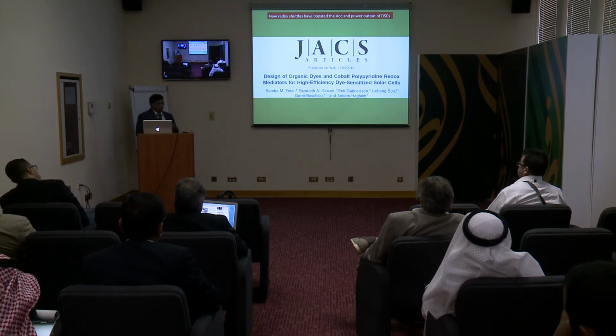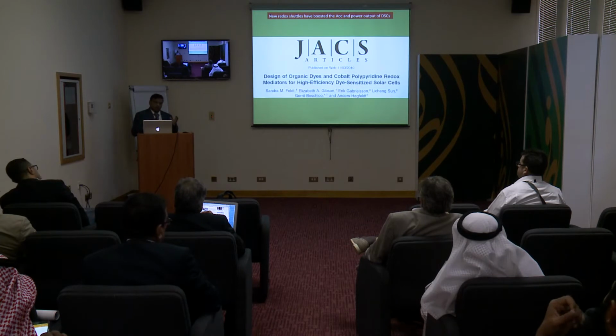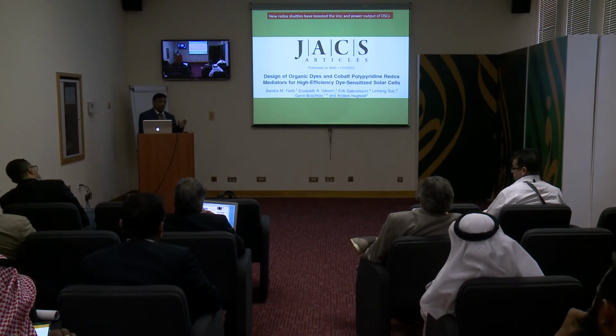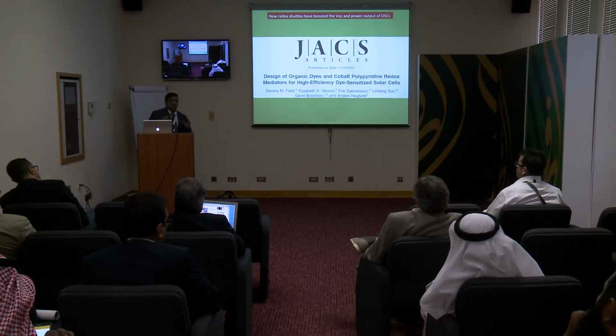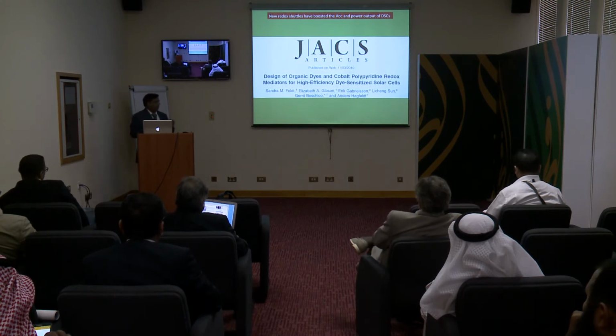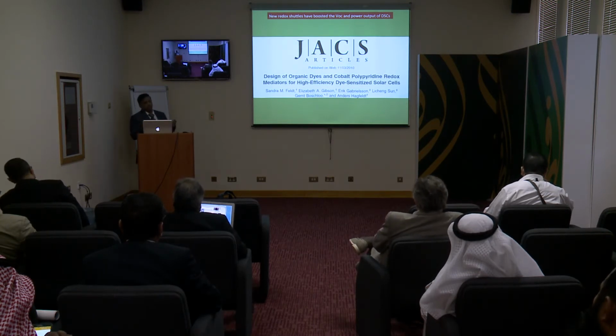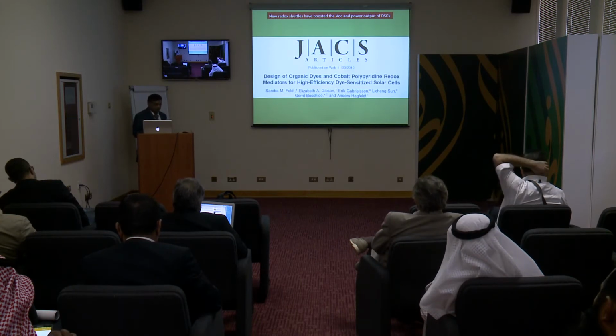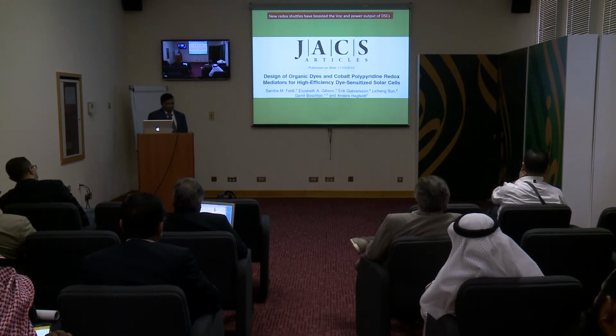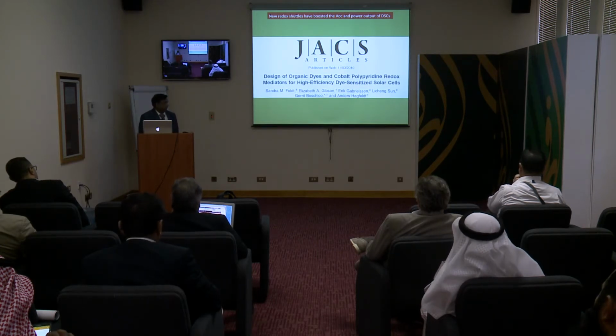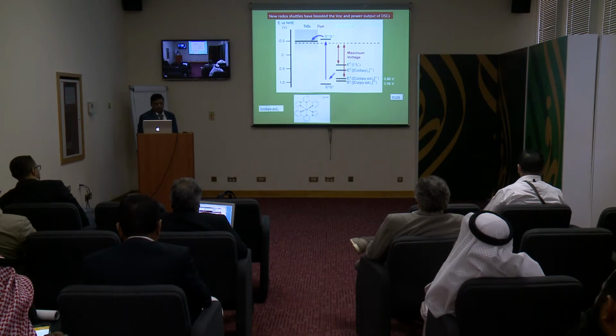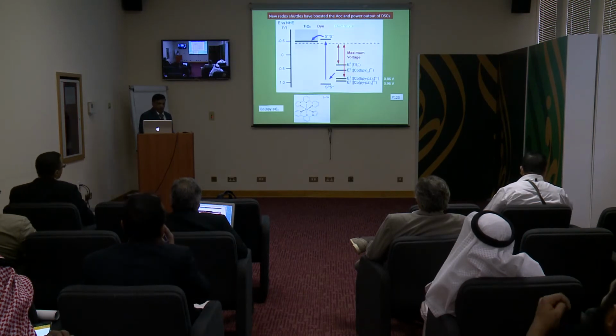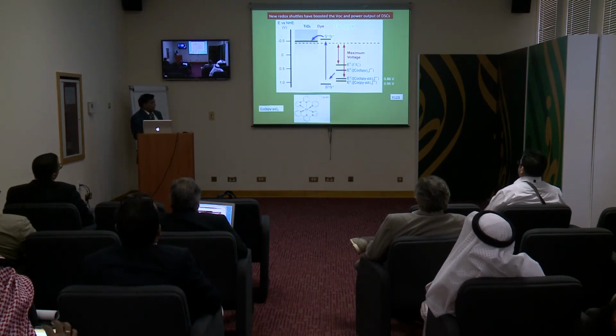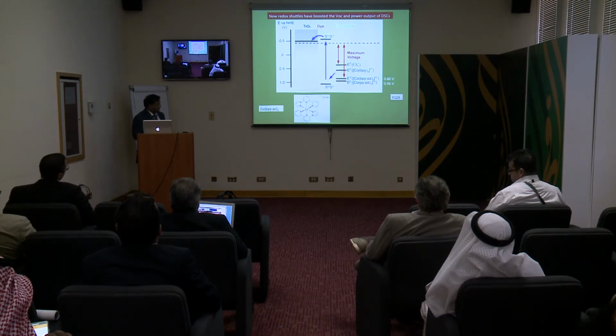they found that by designing the donor of the organic dyes such that there will be a bulky group substituted, there will be less interaction of oxidized species reaching the TiO2. So then you will have less recombination. So from there, it shows how one can use these one electron transfer complexes with the organic dyes. So here you can see how it affects the VOC.